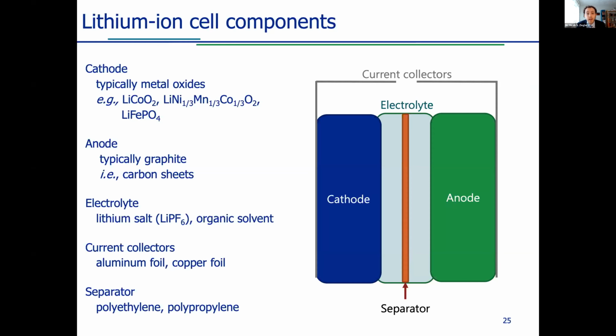On the right-hand side of this slide, I'm showing a simplified diagram of a lithium-ion battery. On the left, we have a cathode. The classic example is lithium cobalt oxide, but over time, researchers have found ways to replace the cobalt with different mixtures of nickel, manganese, and cobalt. We can also use lithium iron phosphate. On the right-hand side of the diagram, we have the anode. In lithium-ion batteries, this is typically graphite, and this is sheets of carbon. And when you charge your battery, the lithium ions migrate from the cathode to the anode and sit between these sheets of carbon. But of course, the lithium ions don't migrate in a vacuum. They need some help moving back and forth.